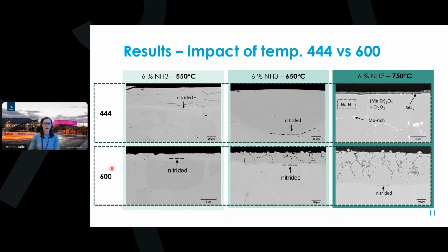In contrast, if we look at the nickel-based alloy 600, we see, as we saw from the mass gain, that with increasing temperature, the depth of nitridation is increased. Also for this alloy, we see oxidation at especially the higher temperatures. But in this case, the oxidation is intergranular and internal rather than forming a continuous surface layer, making it non-protective.